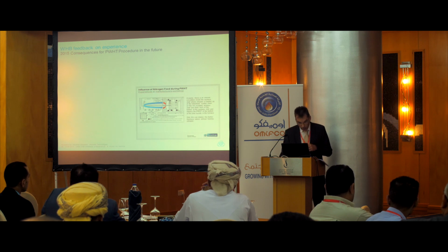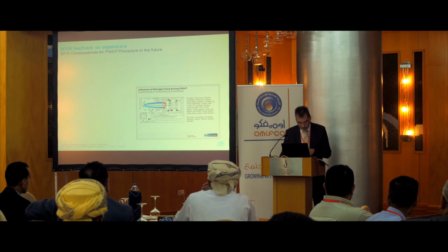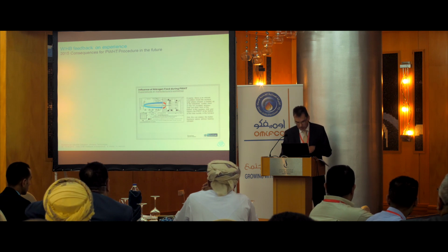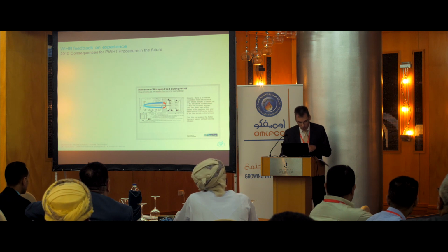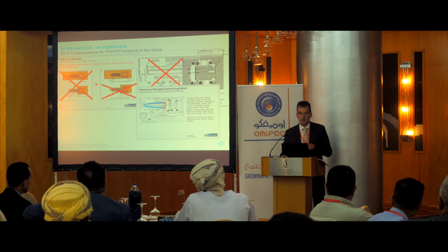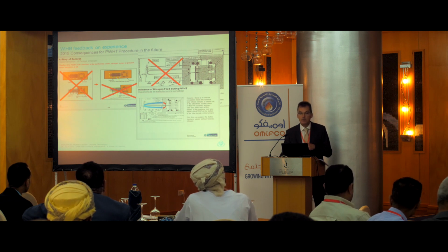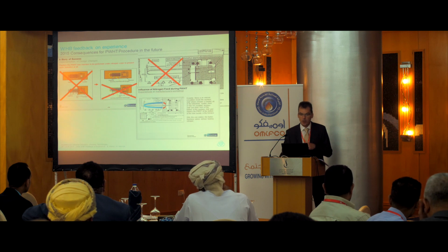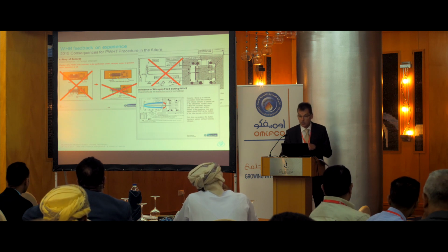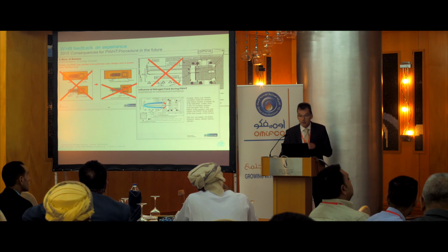In order to avoid any influence by thermal circulation inside the auxiliary shell, when it is partly inside and outside of the furnace, it was decided that from now on it is only accepted to have the auxiliary shell completely inside the furnace. That means in the early stages, in the 80s, the 90s, and 2000, it was possible to do heat treatment if the manufacturer had a big furnace, with the complete waste heat boiler inside the furnace without auxiliary shell, without nitrogen. That was the first. Then we had furnaces with only part of it inside. This was forbidden before 2006, 2007.